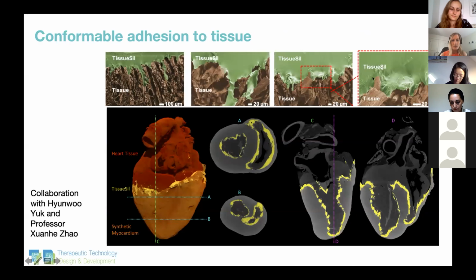This here on the top is SEM images of the adhesive and how it interpenetrates into the tissue, which forms a really nice bond between the tissue and the adhesive, which then can bond to the silicone. So the green there is the tissue sil, as we called it, the adhesive, and this brown layer is the cardiac tissue. Here's a CT image where the red is the heart tissue, and in yellow you can see the tissue sil adhesive. The gray here is the silicone matrix.